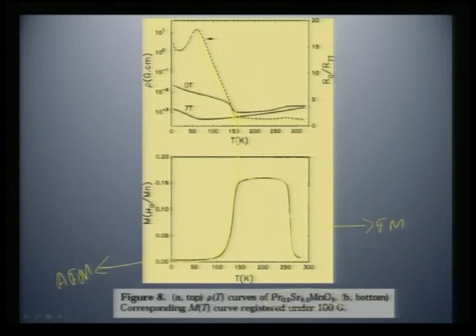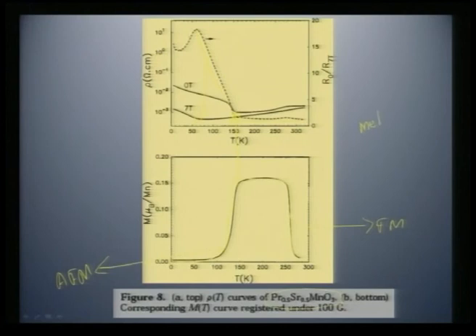Now, what can we do about it? If you try to apply a magnetic field, you can see immediately you can melt down this insulating phase to a metallic phase if you apply 7 Tesla, a very high magnetic field. In other words, you can melt the charge ordering mainly using magnetic field. Okay. There are other reports where you can melt this charge ordering by applying very high pressure.